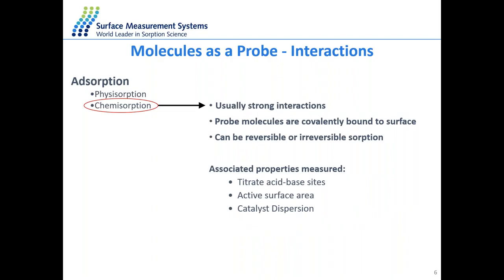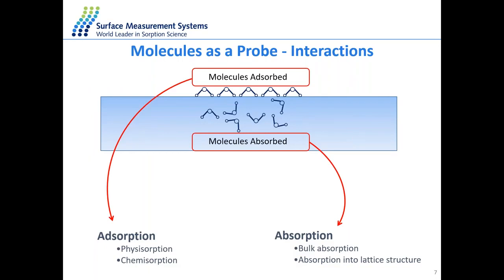With regards to chemisorption, we're looking at more stronger interactions. So this is where probe molecules may actually covalently bind to the surface of the sample. This can either be reversible or irreversible, depending on the strength of the chemisorption. And this is quite interesting because we can obtain other properties, such as titrating acid-base sites, active surface areas, and catalyst dispersion.